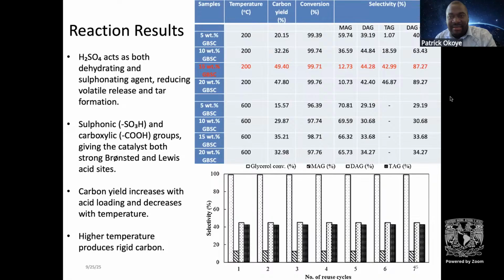So our material was able to produce up to 87% of combined diacetylglycerol and triacetylglycerol. H2SO4 acts as both a dehydrating and sulfonating agent, reducing volatile release and tar formation. Eventually, the sulfonic groups and carboxylic groups, which have high Bronsted acidity, helped us to obtain rich fuel additives as you see here. And this is our material reusability up to 7 times without any decay. This is one of the promising works that we have done so far with carbon material.